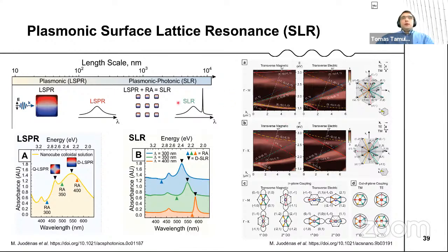So here, I would like to summarize a bit. If we put those nanoparticles that have this localized surface plasmon resonance into a grating that is designed so that the Rayleigh anomaly, which I introduced, is on the left side of this plasmon resonance, we can get the narrowing that is called the surface lattice resonance, these sharp dips. And if we make the angular measurements and transform those angular measurements into these K-space diagrams, we can see that the peaks we are observing are nicely following the trends that are expected from the photonics, from this regular fashion of those structures.